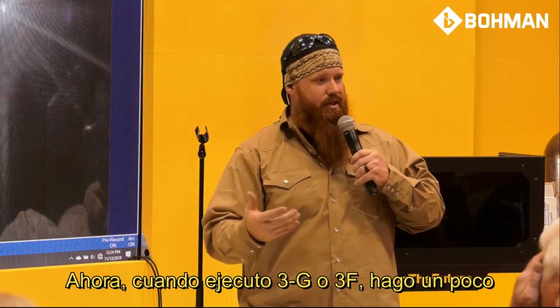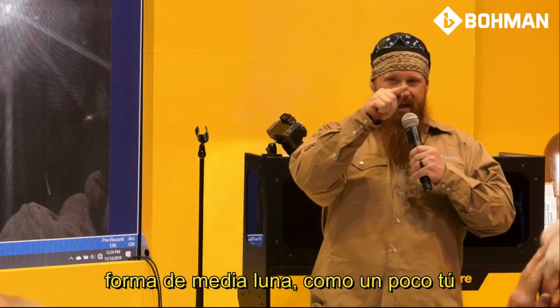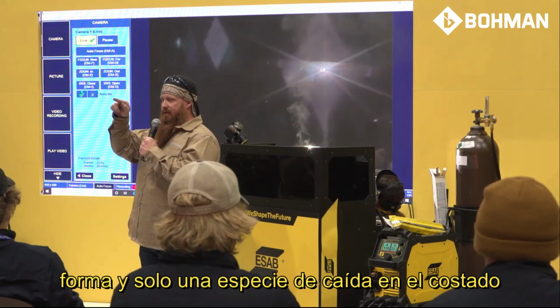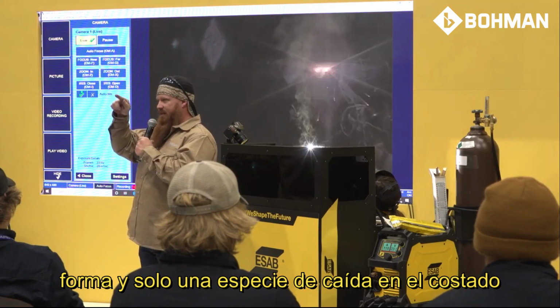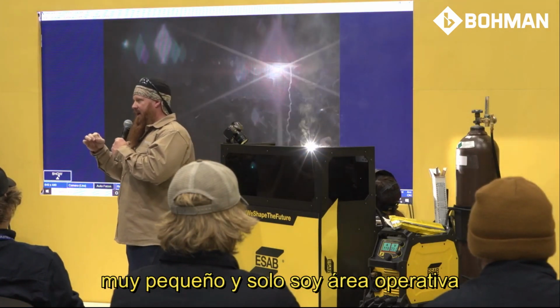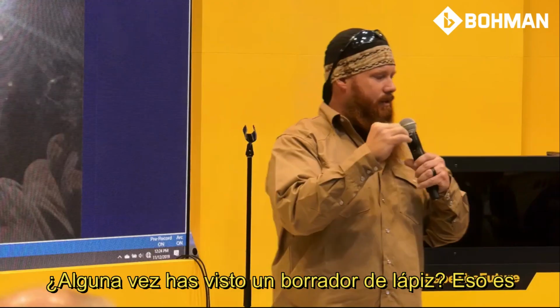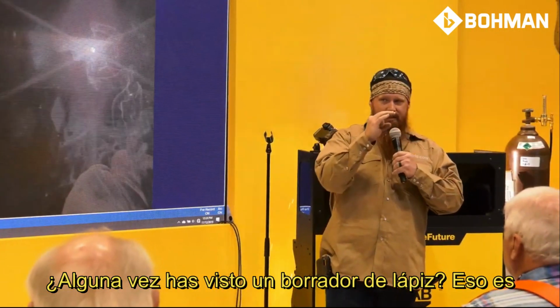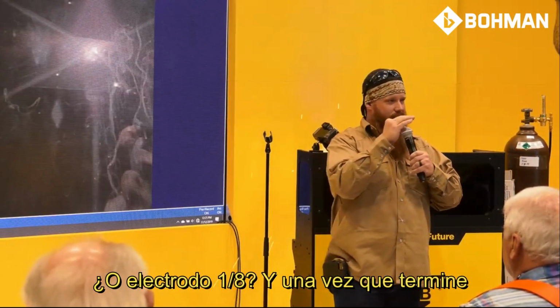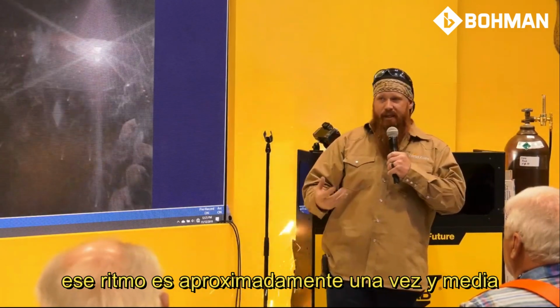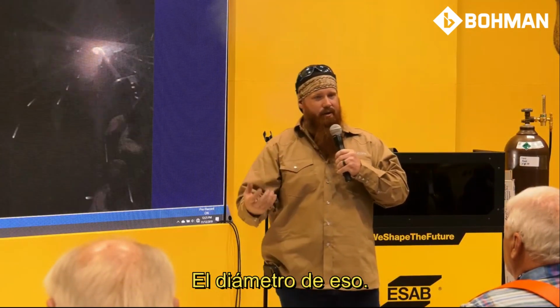Now when I run 3G or 3F, I do a little half moon shape or like a little U shape and just pause on the side, very small. I'm only operating in an area about the diameter of a pencil. If you've ever seen a pencil eraser, that's about the area that I'm operating in with a 1/8 electrode. Once I get done, that bead is roughly 1.5 times the diameter of the rod. So with a 1/8 inch rod, I should yield about a 3/16 wide welding stringer. And I'm just going to keep running multi-passes.